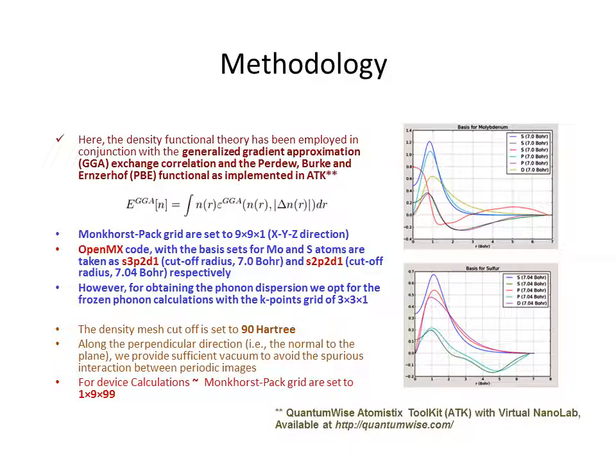In the study, first principles based density functional theory DFT calculations are performed using the software package called Atomistix Toolkit or ATK. Density functional theory has been employed in conjunction with the GGA-PBE. We use OpenMX norm conserving pseudo-potentials with pseudo-atomic orbitals and the medium basis sets having cutoff radius of basis functions around 7 bohr.